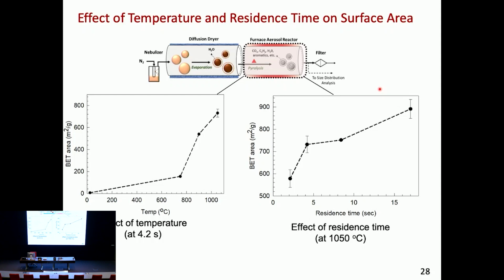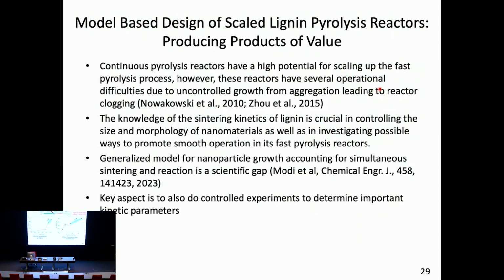I can choose, let's say, and of course the goal here, depending on what application, I want a high surface area material, so I pick the largest temperature and vary the residence time. Now the dynamics takes place, like at low residence times, I won't have collisional growth and things like that, no sintering, but you also see that there's not sufficient time for the chemical reaction to take place. That's where the quantitative comparisons come in when I really want to explain this data. But the net is I can make high surface area carbon nanoparticles, because I got to keep in mind my application folks who want to use some of these particles. But simple studies like this in a laboratory system give me these things.